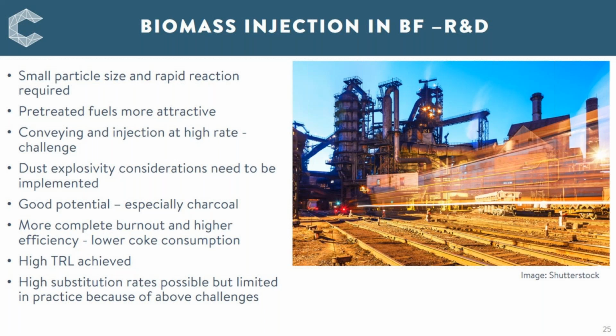The research has shown that it gives more complete burnout than some of the coals that are used, which means that it's higher efficiency. So it lowers the coke consumption. There's less coke being used to provide thermal energy because you've got good reaction of the charcoal in the hottest parts of the blast furnace. And actually high technology readiness level has been achieved, and I've got a case study to show that in a moment. So in theory, high substitution rates are possible, but actually in practice, it's limited by these points of how much you can actually convey and inject at the high rate that's needed.